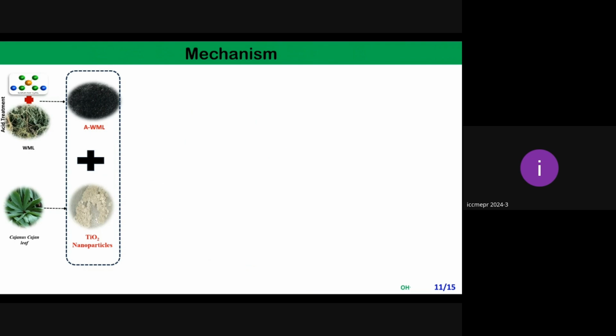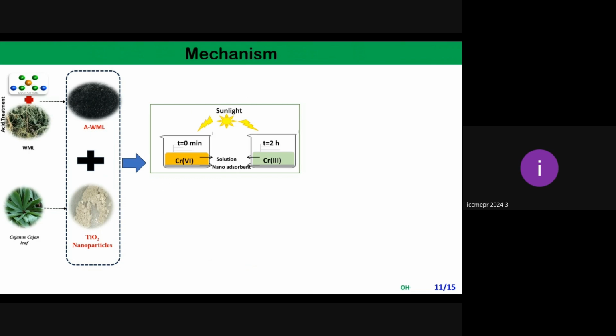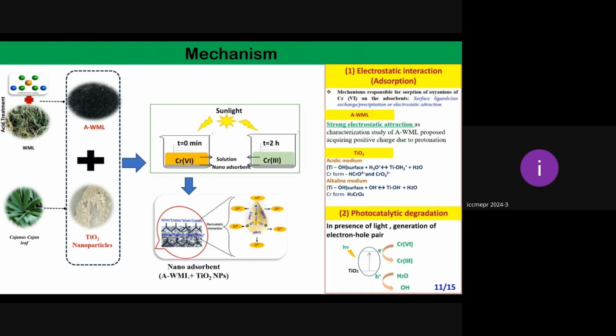So before coming to the performance of the prepared nanoadsorbent for removal of hexavalent chromium, let us first understand the mechanism behind it. When AWML is mixed with TiO2 nanoparticle in a definite proportion and kept under sunlight, two mechanisms are there for removing and reducing hexavalent chromium to trivalent chromium. First, electrostatic interaction, due to the adsorbent material and the TiO2 nanoparticle both exhibiting different charges on their surfaces due to protonation. And when hexavalent chromium gets adsorbed on the surfaces and is kept under sunlight, due to the photocatalytic activity of the TiO2 nanoparticle, this hexavalent chromium gets converted to trivalent chromium because of the generation of electron-hole pairs.